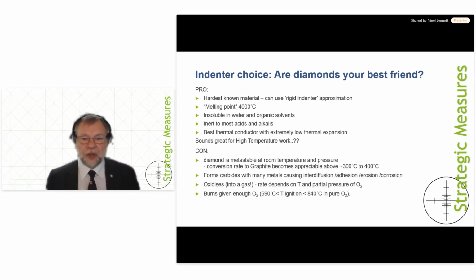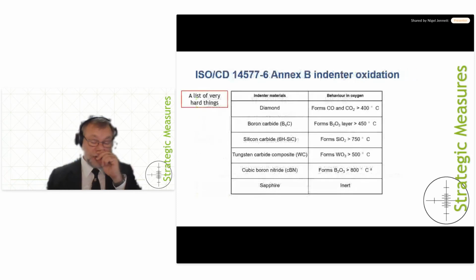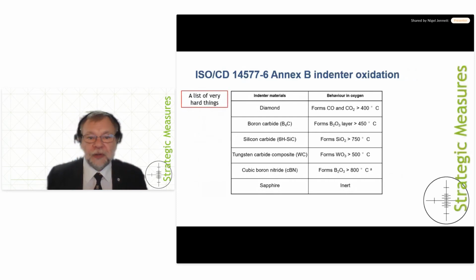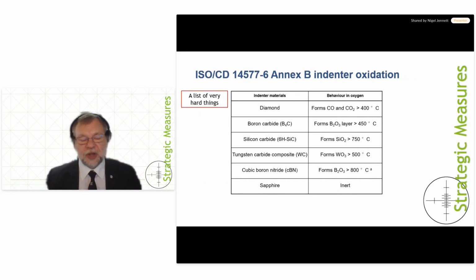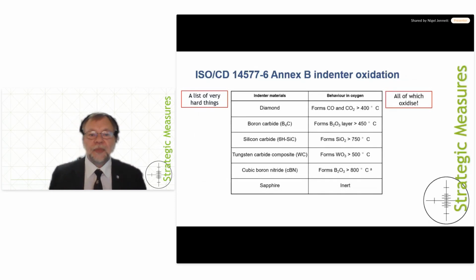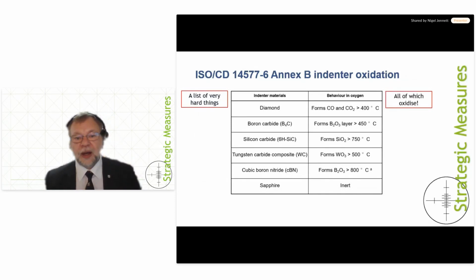Now, it doesn't take an awful lot of material removal at the very tip of an indenter to radically change the area function. So whilst this might seem to be a small problem, it is actually a small problem with quite large consequences, and therefore you have to think what to do. So in ISO 14577 part 6, there's a list of very hard things which you might try to use as an indenter instead of diamond. Sadly, nearly all of them oxidize at some point or other. However, you do have some temperature limits that are a bit higher than the 300 or 400 degrees Celsius of diamond, and so you have an opportunity to do higher temperature indentations.